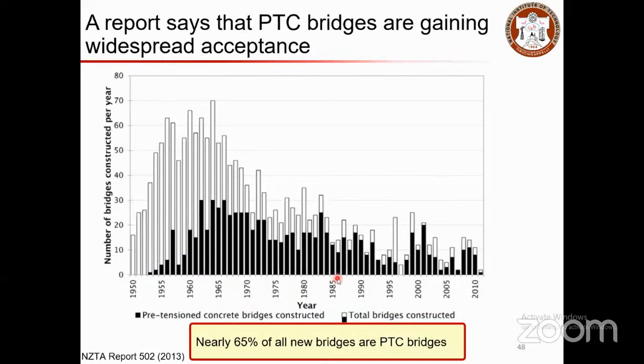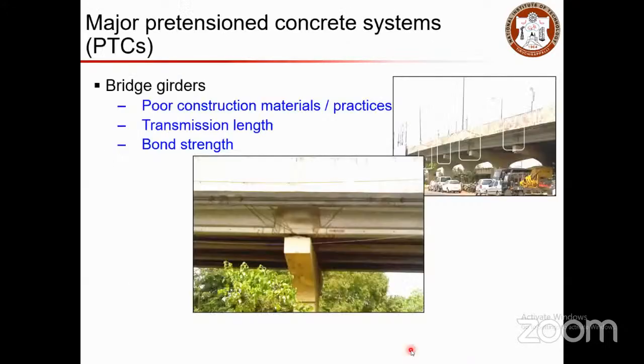Nearly 65% of all new bridges are constructed using pre-tension concrete technology, owing to its advantage of having long members, slender members, and reducing the cracks. Obviously. But then we have observed a few issues with the pre-tension concrete system itself. This is one of the bridges connecting Pune to Mumbai that has a lot of shear crack formations in the girders, almost all along the length of the span. So what could be the reason? Unless we examine these structures, we cannot provide a solid reason.